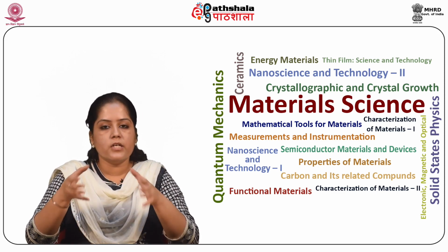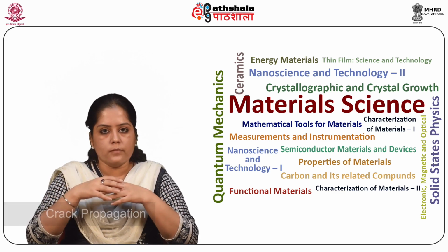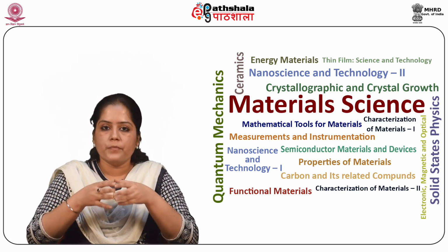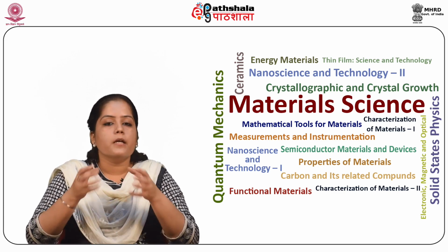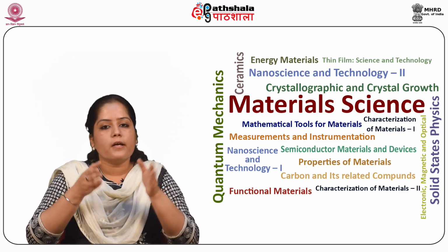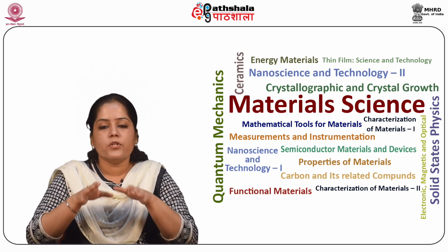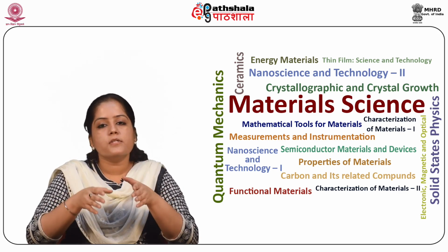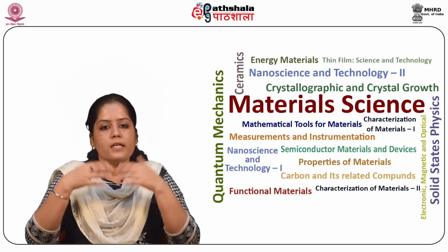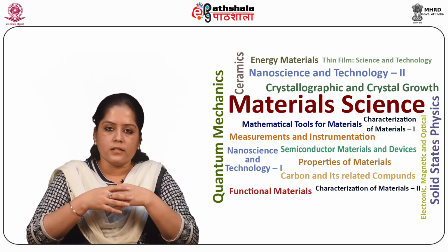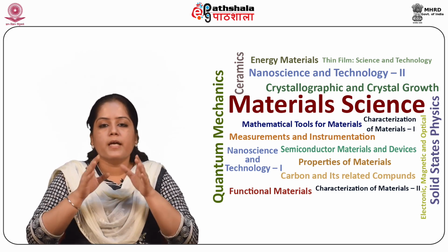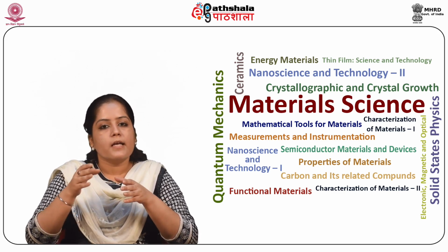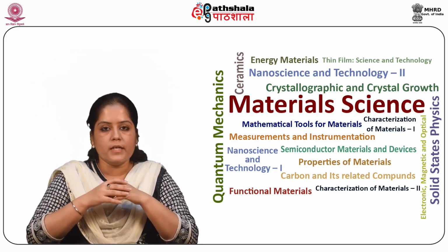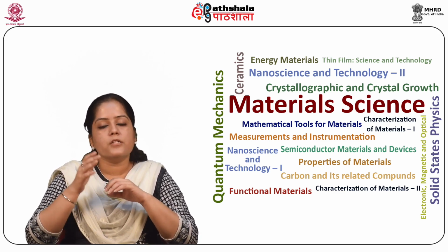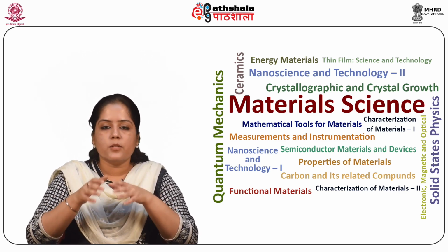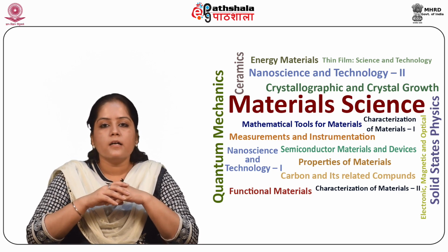Toughness depends on the energy consumed during crack propagation. So any microstructural feature which impedes the crack propagation, requiring more energy consumption for crack propagation, or any process which introduces stresses which oppose the applied stress, would lead to an increase in the toughness. On this basis, the mechanisms for toughness increase can be categorized broadly into the following categories. First, the crack tip interactions. Second, crack tip shielding. And third, crack bridging.